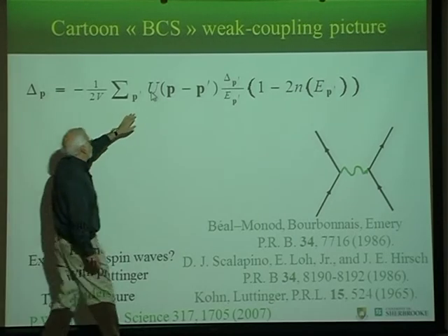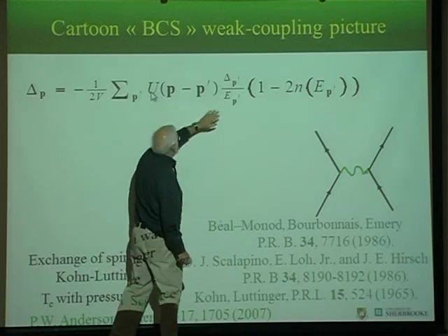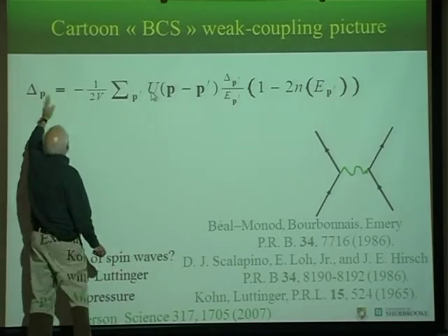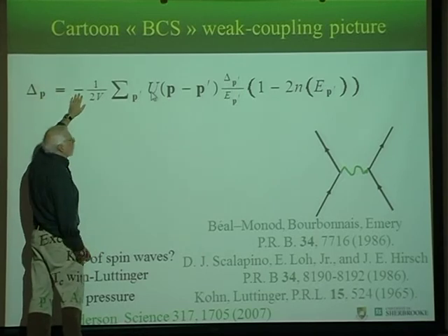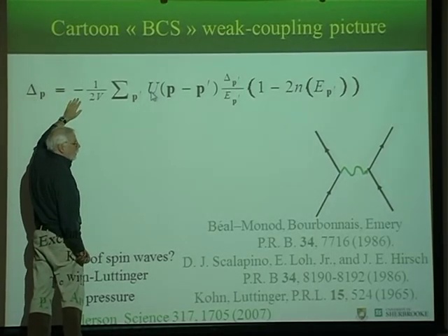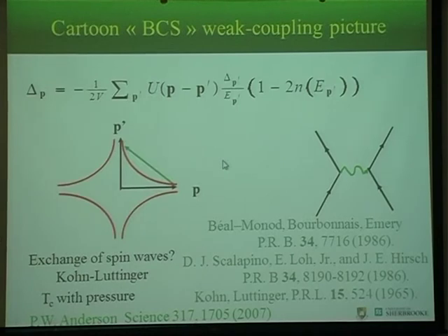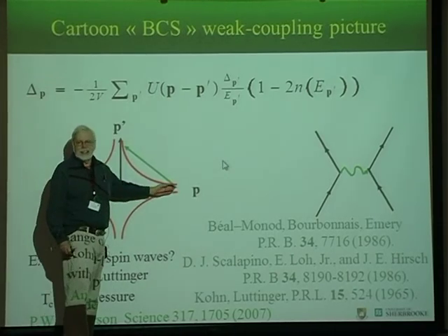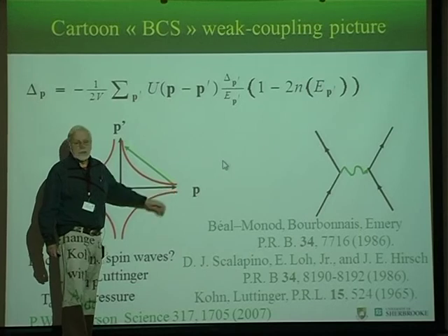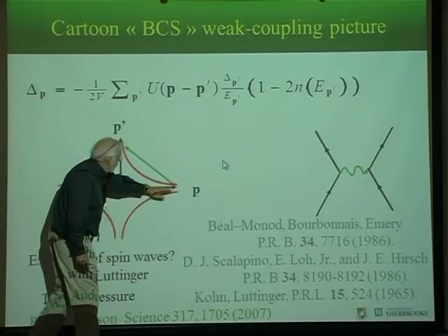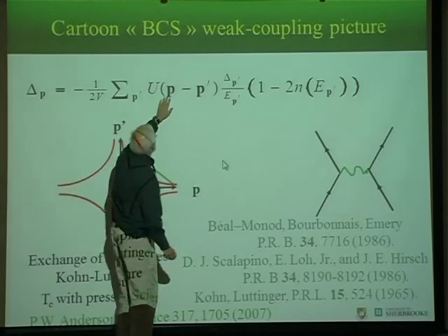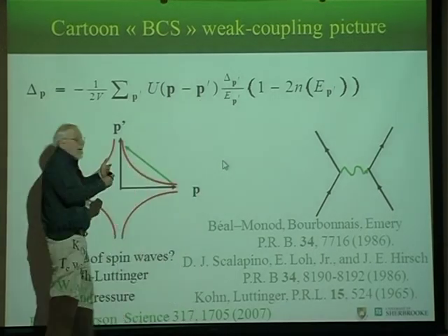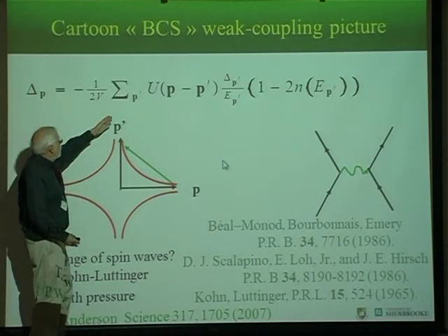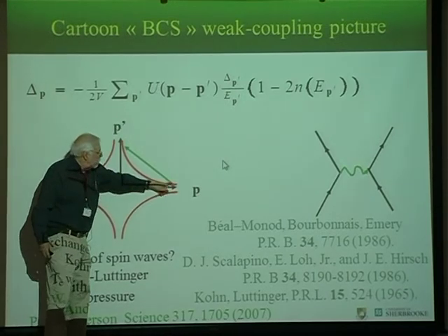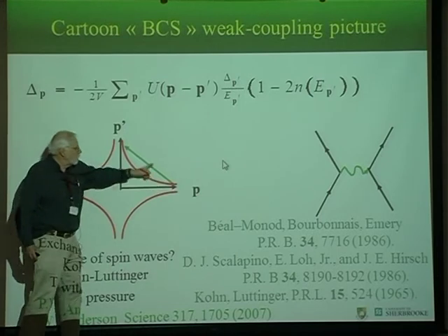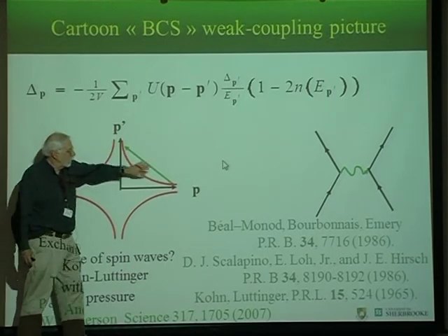If U is positive, then everything else on the right is positive. And then there can be no S wave solution because you have a positive number equal to a negative number, or negative equal to positive. Now the way around this is if there is some momentum dependence in the wave vector, in the gap. Suppose I look at the gap in the direction P here, and suppose that this is very large at pi. So it means that the dominant term in the integral here will be the term that goes from here to here. So it will be a P prime that's connected to P in this way.